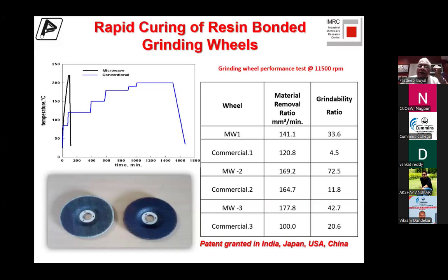This was our really a big project that we took up to see that we can rapidly cure grinding wheels. Grinding wheels are used all over in every industry that you can think of. They are used for cutting steel, they're all kinds of things. Now here you see this graph. The conventional is the blue one. So the grinding wheel is so thin, it's like 2 or 3 millimeters. And if you try to heat it very fast, it will crack. The green grinding wheel will crack.